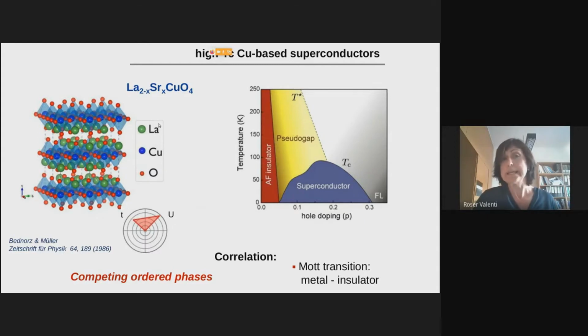And when we are in the case of what we call the stoichiometric materials, so x is equal to 0, La2CuO4 in this case, the system is an insulator and shows long-range order. So it's an antiferromagnetic insulator, but it's what we call a Mott insulator, because the reason why the system is an insulator is due to the strong Coulomb repulsion that the copper d electrons feel. And because of this strong Coulomb repulsion, the state that the system shows is a very localized state, so it becomes an insulator.